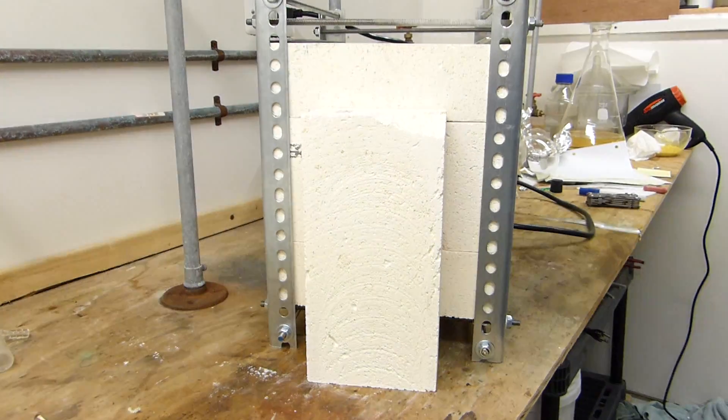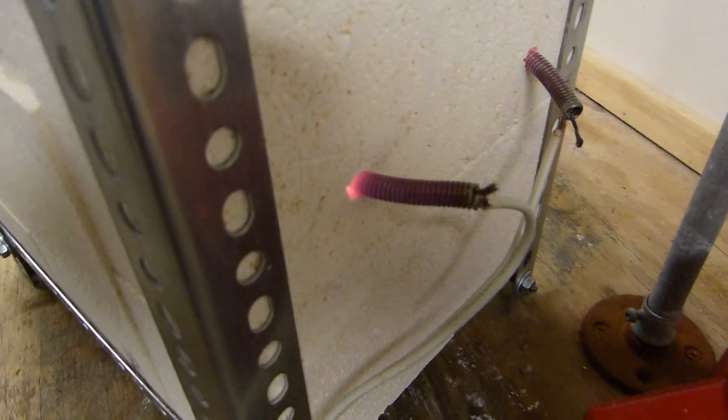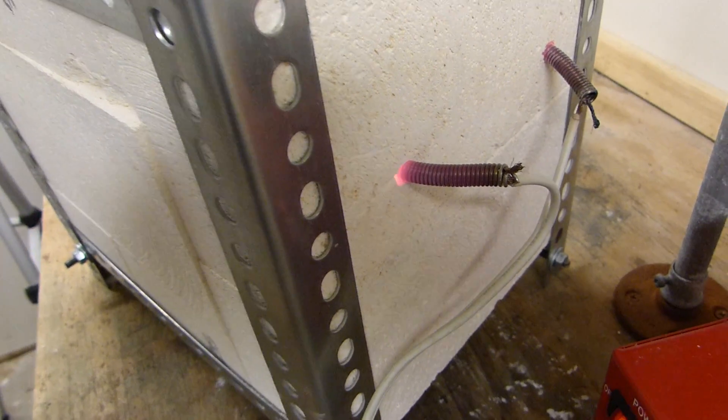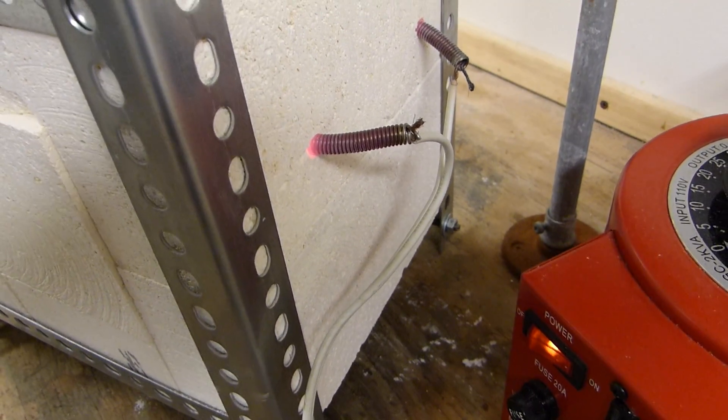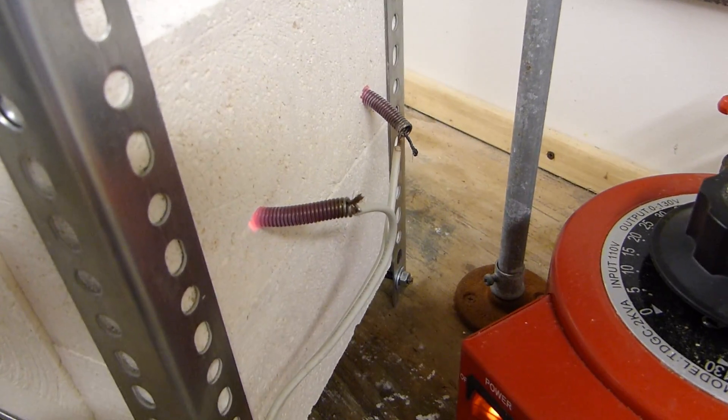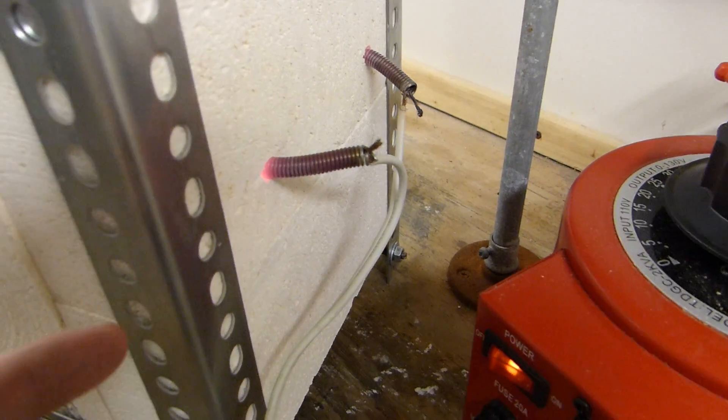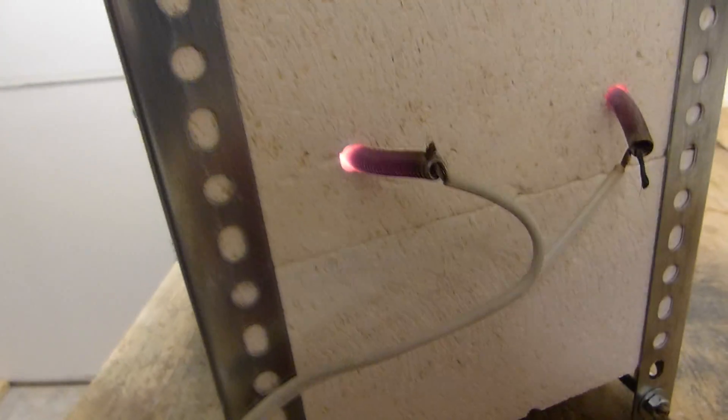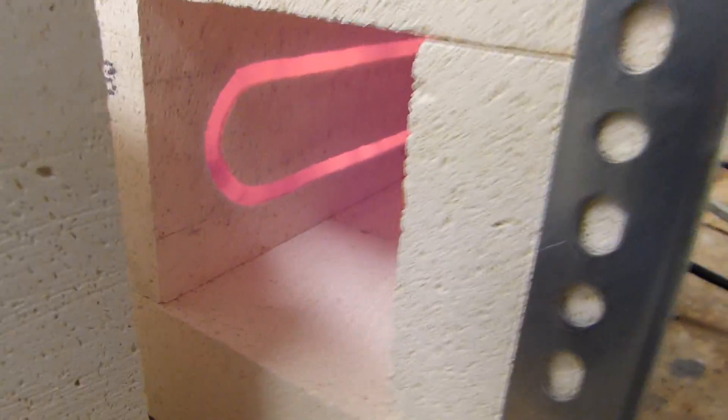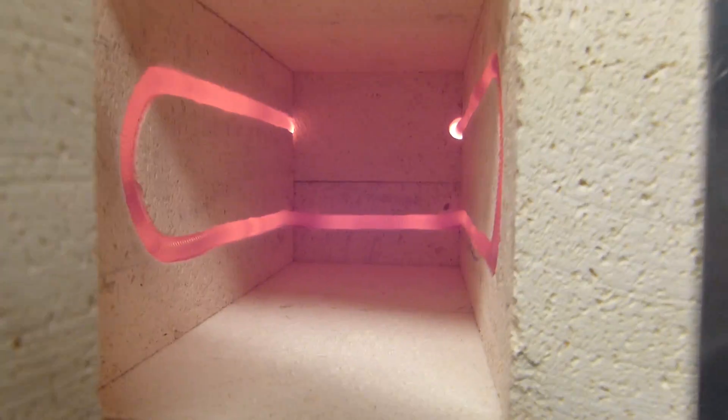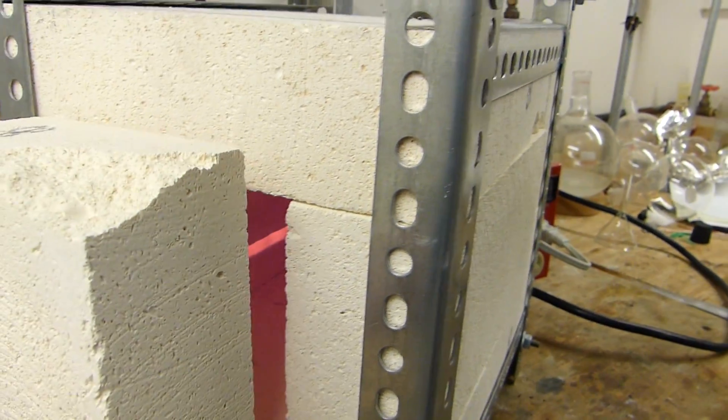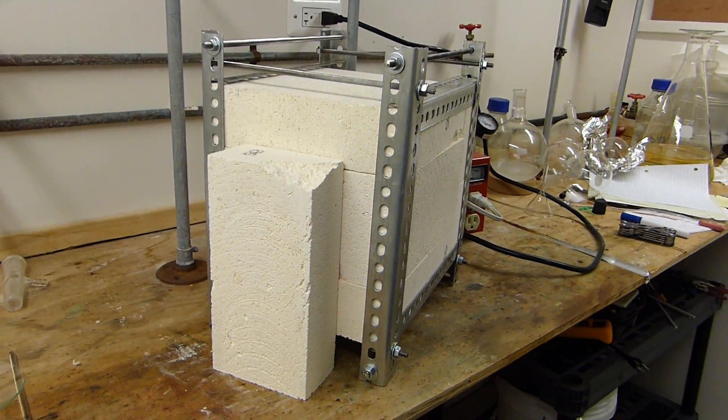A few kinks to work out. I think the way that the heating elements are routed through the brick in the back, they get quite hot right there. And it's not a problem for the connection, really, but it is a problem for the heating element. That's the hottest spot is where it passes through that brick. So what I want to do is create some custom, basically thick copper plugs that jam down inside those elements, which will keep the contact point pretty much inside those bricks and hopefully draw some heat out of that, because that's going to be the failure point right there. Other than that, though, this is working out pretty well. I'm going to stick something in there now and see how hot I can get it.